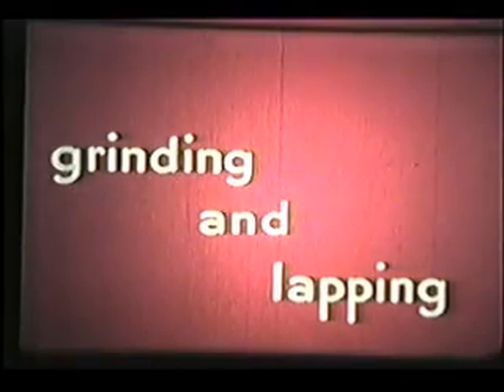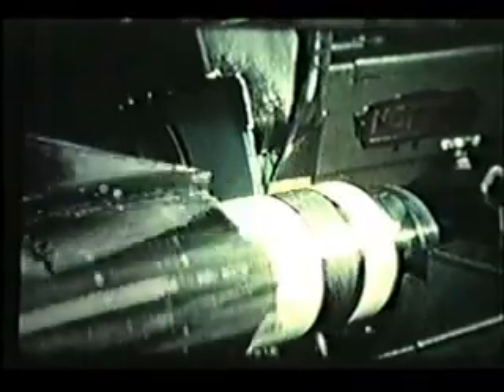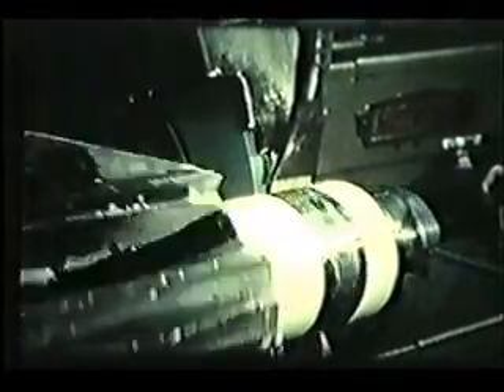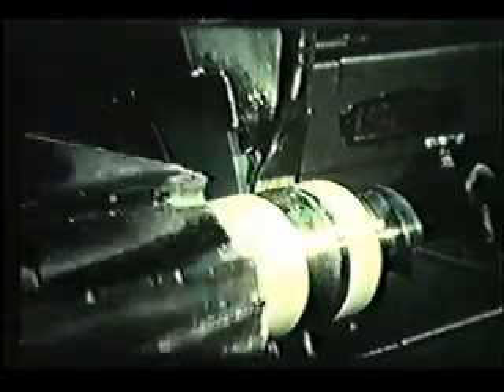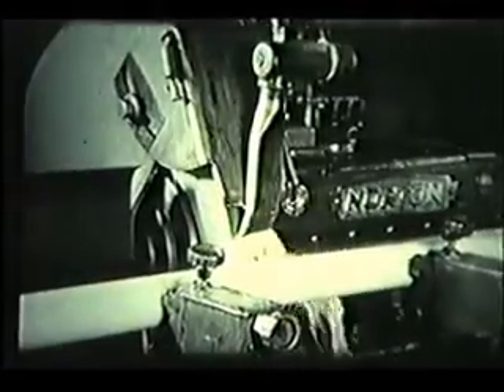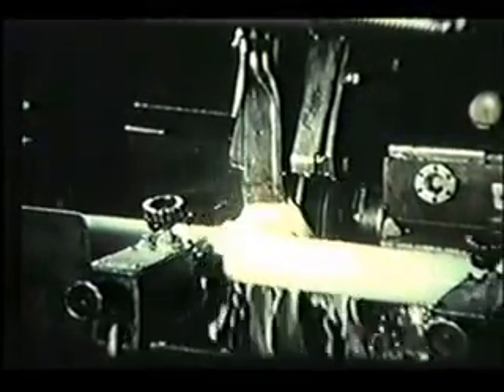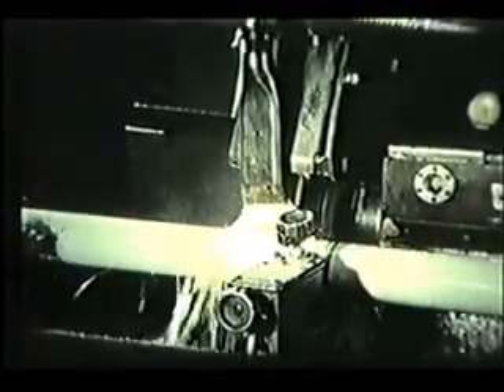To achieve close decimal tolerances and excellent surface finishes, grinding and lapping of the coatings may be required. An impregnated Rockide ZS bearing surface of a rotor used in a paper making machine is being carefully ground. This results in a hard, smooth, corrosion-resistant surface and was developed to extend its life when used wet against a Teflon sleeve. Grinding on these long printing rolls is accomplished with silicon carbide grinding wheels, resulting in an excellent 30 to 50 RMS finish on Rockide ZS. Previous wear life with hardened steel was 1 week, but with Rockide, 1 year.